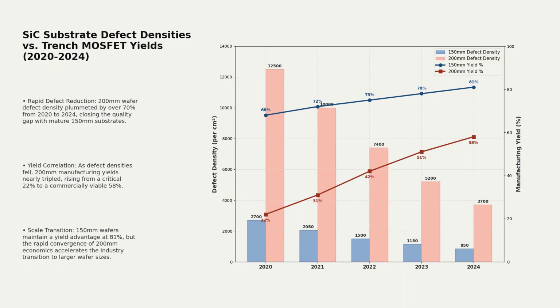The transition from silicon to silicon carbide is essential for high-voltage grid infrastructure. However, scaling production from 150mm to 200mm wafers has introduced severe crystallographic defects. In 2024, defect density on 200mm substrates averaged 3,700 defects per square centimeter. This is more than 4 times the density of mature 150mm lines.